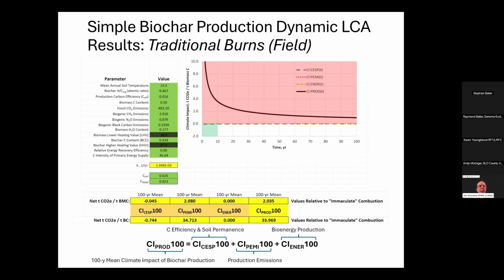Then the next three are biogenic emissions for methane, nitrous oxide, and black carbon. For this one, 2.9 grams per kilogram for methane, 0.079 grams per kilogram for nitrous oxide. Now I should mention the nitrous oxide, there are no data collected for nitrous oxide per se, so we just used a very crude estimate by taking the NOx values and multiplying them by 0.1 on the assumption that nitrous oxide generally is much smaller than NOx, but it kind of scales with NOx. One of these days we'll get a nitrous oxide analyzer on this system and we'll be able to get really good numbers. The black carbon emissions are based on the aethalometer values that Stephen reported.